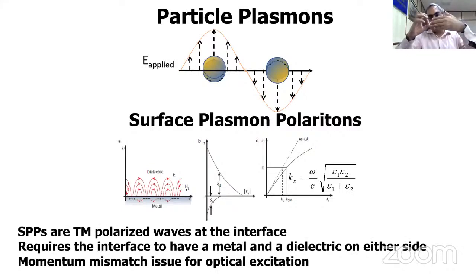Now, when you shine light on this nanoparticle, there is absorption into this resonant oscillation of electrons, and those particular frequencies are dropped because they're absorbed into the particle plasmon. So you'll get some scattering colors from these nanoparticles. You can see this, for example, in the colorful windows of old buildings. These are metal nanoparticles, but they are coated with different salts in general. But the idea here is that because this radiation is localized to the surface of these metal nanoparticles, these are called particle plasmons.